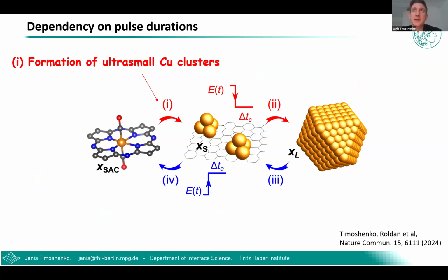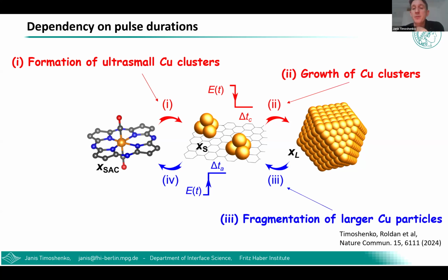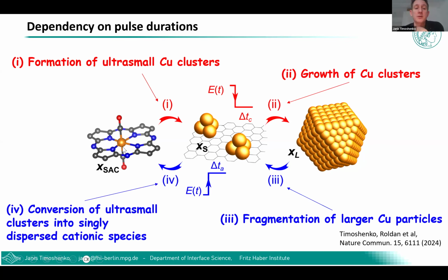So by combining all this insight from operando investigations, we can conclude with a simple model of what happens with this catalyst. So we start with the singly dispersed structures, and under negative applied potential, we first form very small atomic clusters of copper dimers, trimers, and so on, which then gradually can grow into bigger and bigger particles. But once we apply positive potential, these bigger particles fragment back to smaller ones, and then eventually these smaller particles are pulled apart again and form the original ultra-dispersed, singly dispersed cationic copper sites. And once we repeat this pulse sequence, we repeat all of these 4 processes again and again.